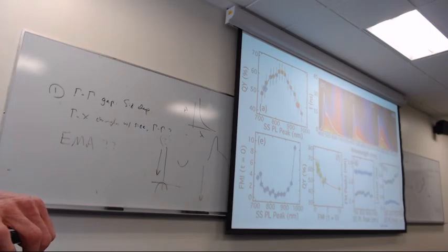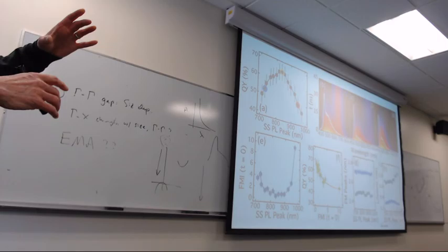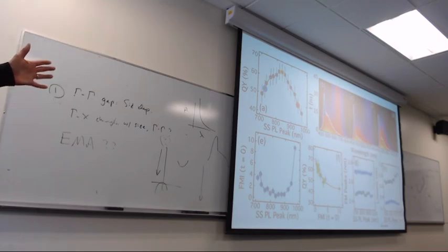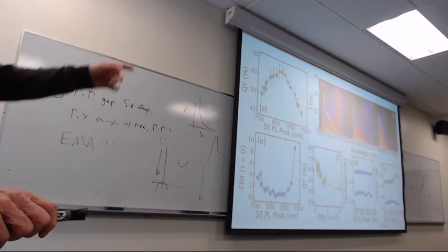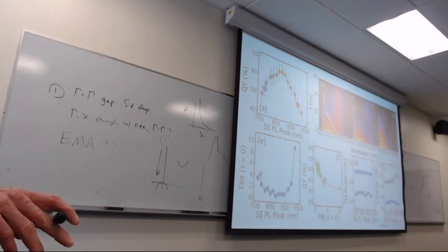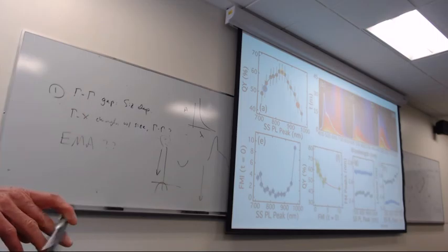They have excitonic effects, I mean, it's in there. Oh, they already included it. There's a term for the electron-hole coupling. I wish I had my computer, I could show you, but the agreement is uncanny and no one's ever seen it before because everybody else's dots are oxidized. So they're actually really big, but the core is really small. So when they go to do the gap versus size, they use the big size and the big gap, and it skews the whole curve off. That's the first thing we noticed: God, these dots are small for red emitters. That's because they've never seen oxygen, right?